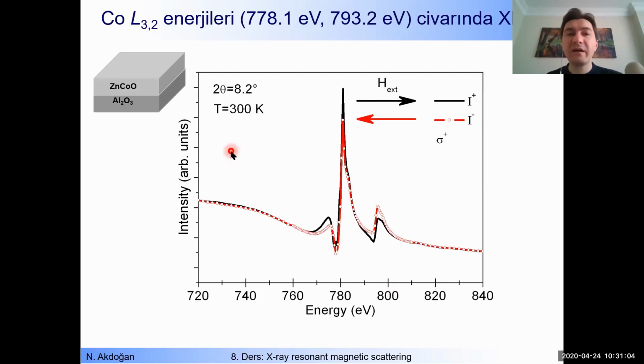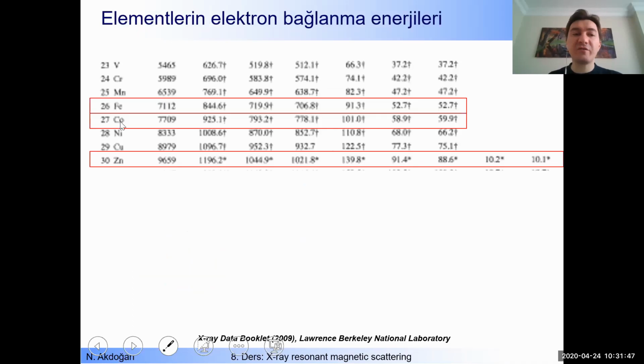Here we have XRMS scans for cobalt L3 and L2 energies for a fixed polarization. We use right circularly polarized light here, and then 2 theta angle is equal to 8.2 degrees, then theta angle is 4.1 degrees, temperature is fixed at 300 Kelvin, okay? And then we have energy range between 720 and 840. Why this range? If you would like to investigate cobalt within that material, you have to catch the energies of cobalt. Here we have 778 for the L3 edge and 793 for the L2 edge, right? So you have to see that energies.